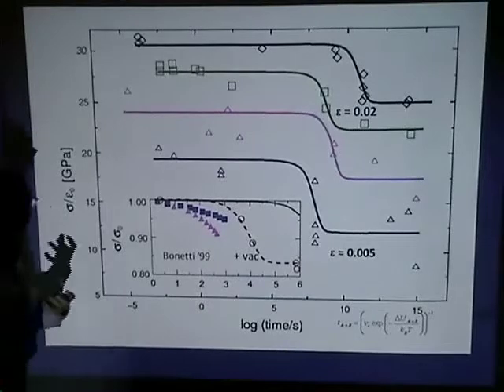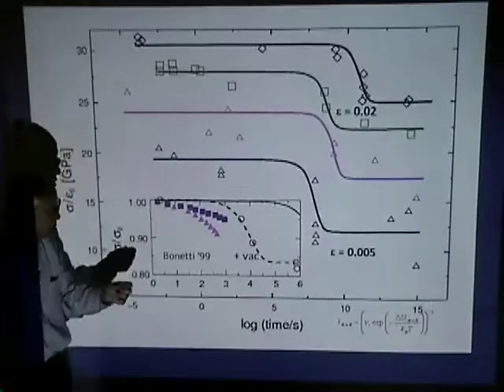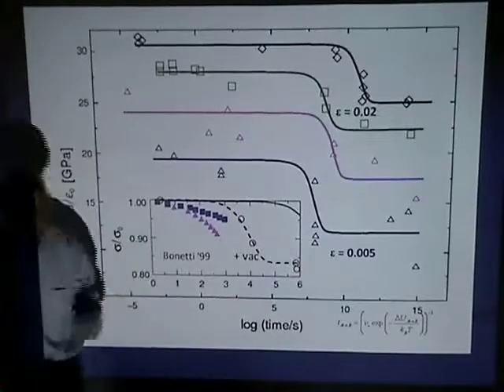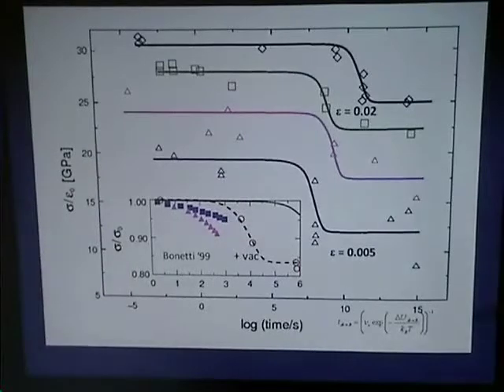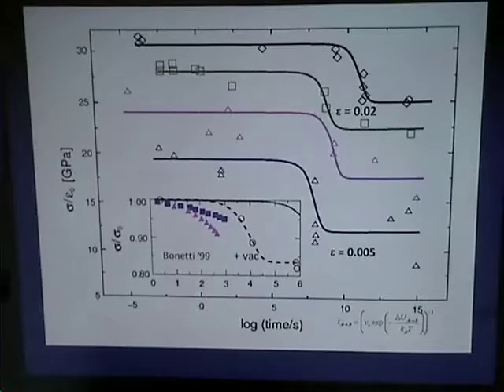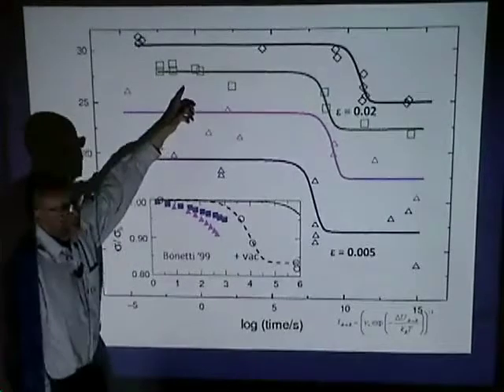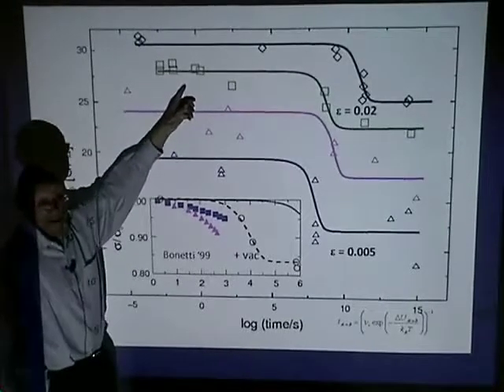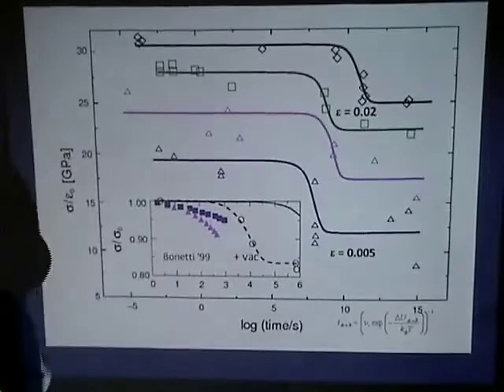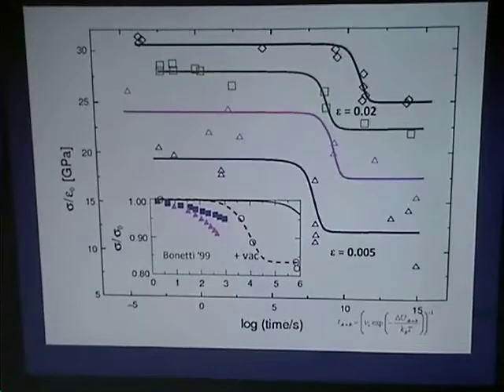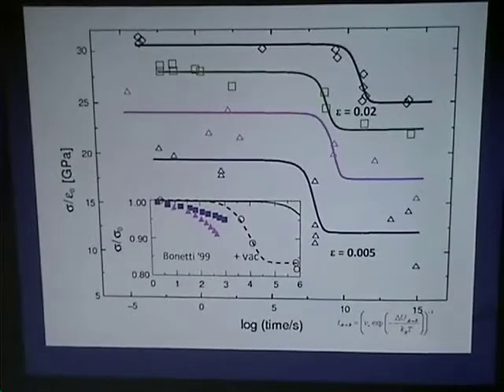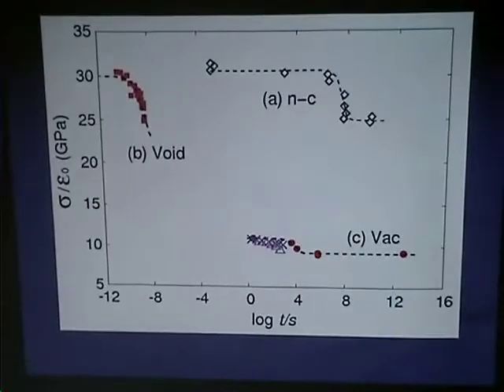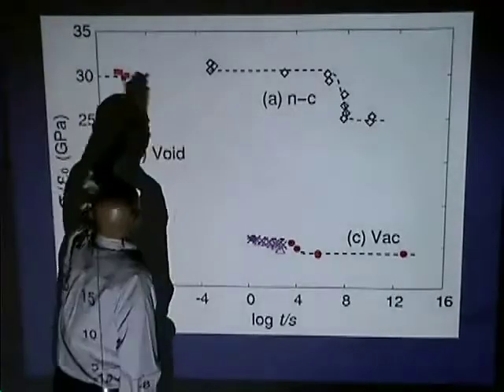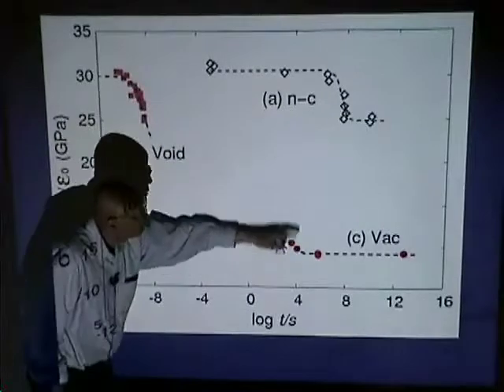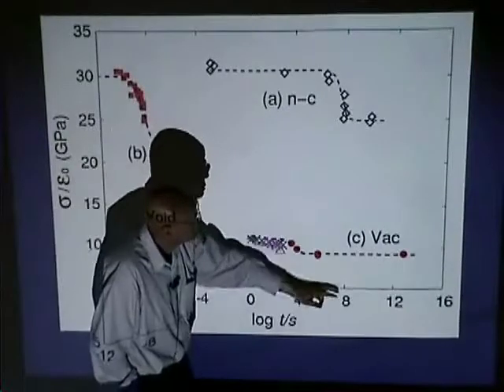Experimentally, they measure, using mechanical spectroscopy, relaxation times of the order of 1,000 to 10,000 seconds. Way, way off, and we understand that. That's because our simulation cells are too pristine. As soon as we introduce some additional defects, like some vacancies into our system, for example—this was the pristine case, high stress, very, very long relaxation time, of order 10 to the 8th.